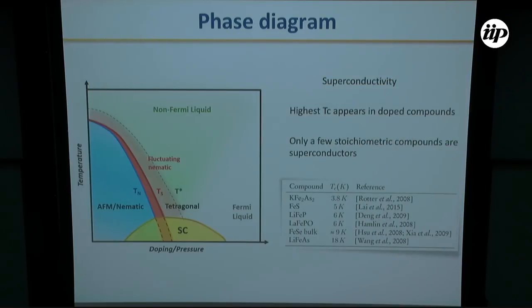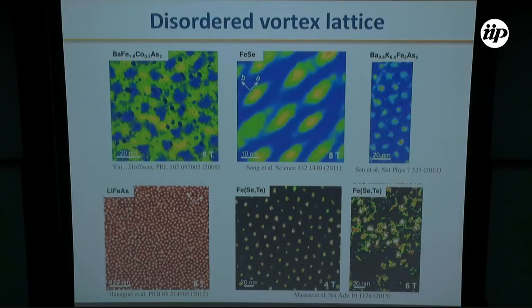Although I have said that the highest critical temperatures appear in doped compounds, there are also stoichiometric iron-based superconductors. Here I show you a few examples, but more often they show very low critical temperatures. So it would be ideal to have the possibility to study one stoichiometric compound with high critical temperature to investigate the intrinsic properties that lead to the high critical temperature in these materials.